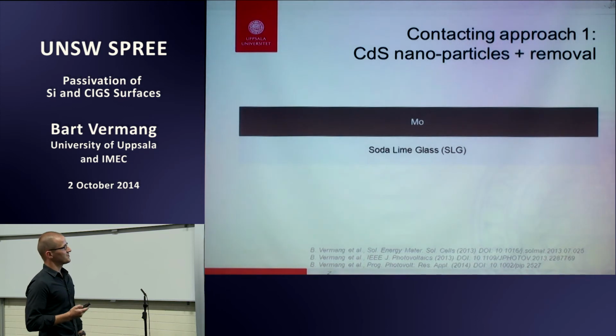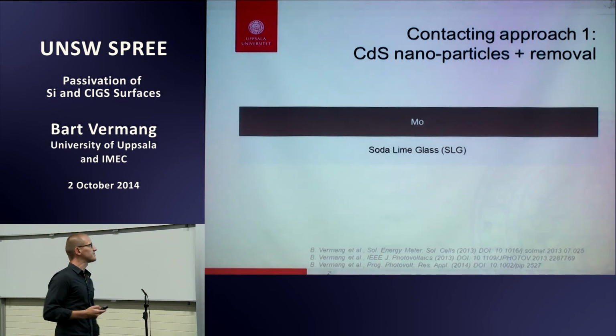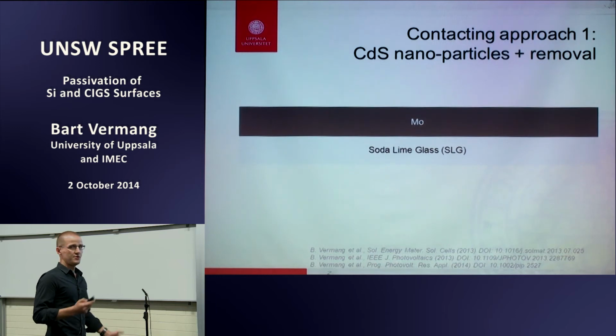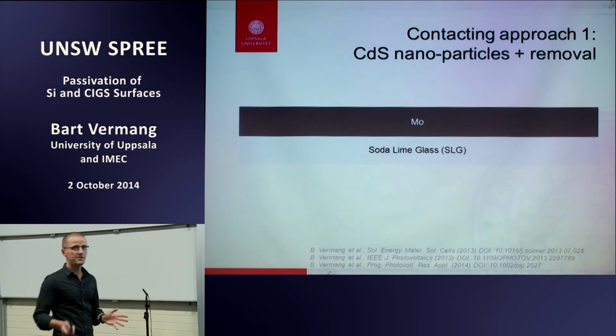Now the challenge was to make the openings, the nano-sized point openings. So we had to come up with a few innovative ways to still have it kind of industrially viable for the future, but still have 200 nanometer openings. Typically, diffusion lengths in CIGS are 1 to 2 micron, let's say, 2 micron for very high efficiency cells or absorber layers, and then lower for lower quality layers.